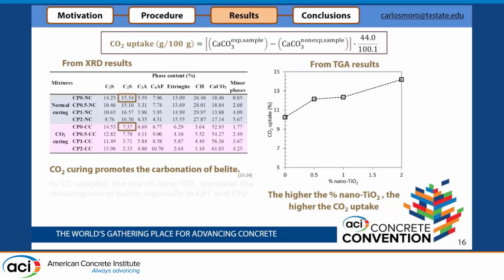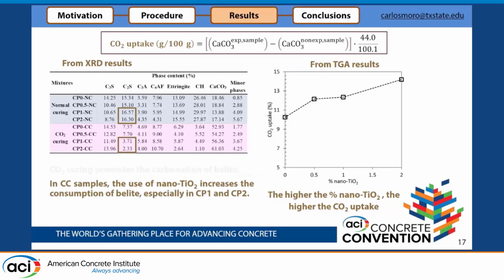And we saw that not only the CO2 curing promotes the carbonation of belite, because in our samples with CO2 cure, basically our percentage of belite is almost half. But also if we add higher amounts, the highest amounts in this study, 1 and 2% of nanotitanium dioxide, this carbonation of belite is even further increased. And we are basically using all the belite remaining in the samples, and we are basically producing CSH on that. That's a good sign because also this belite is very slow reactive. That means that we are accelerating the whole process to further improve the properties.